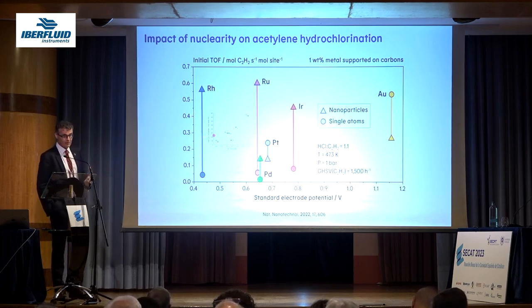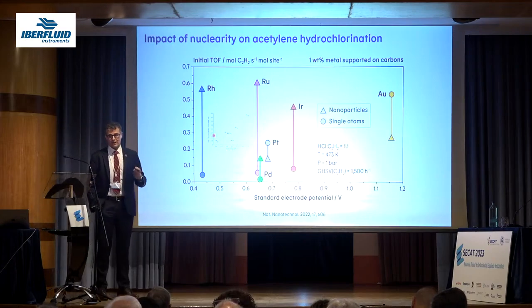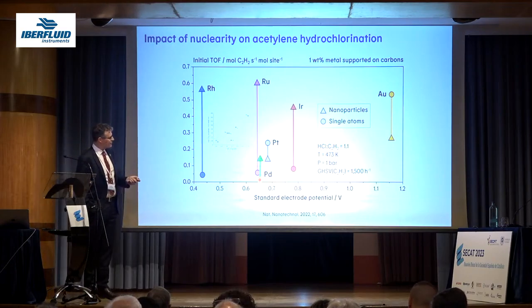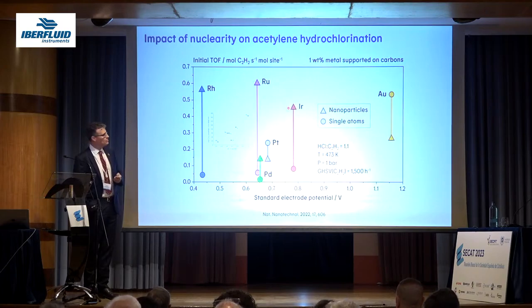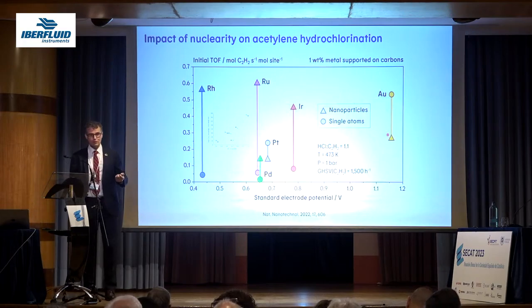And what we could see is actually that this correlation that was found between the electrode potential and the conversion, actually there is no correlation. Because it's very sensitive to the nanostructure. Ruthenium nanoparticles are amazing materials. Ruthenium single atoms are terrible materials. The same goes for iridium. On the other hand, gold single atoms are wonderful catalysts, but not the same for gold nanoparticles.